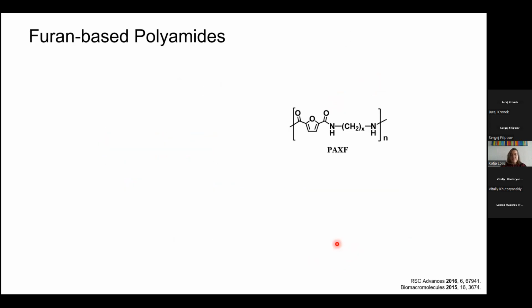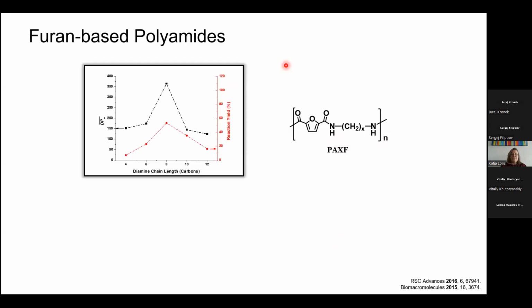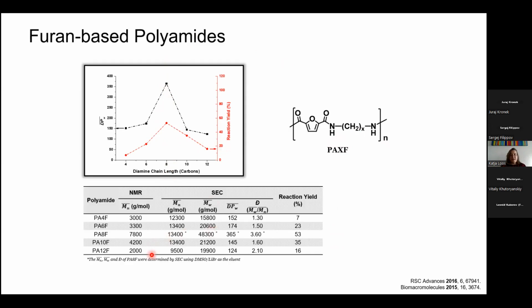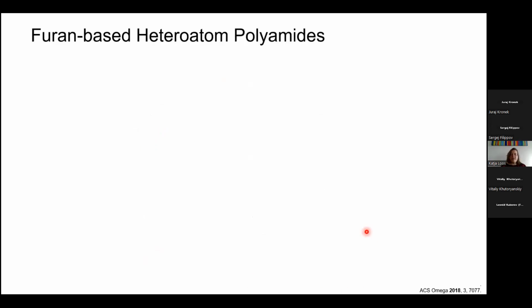And again, also here we screened different diamine lengths, and you see again that the enzyme prefers a diamine with a length of 8 carbons in the chain, and this is again sort of the natural length that it's used to from the fat in nature. And yeah, you see again, we don't get the highest molecular weights because of solubility issues, but it's in principle a reaction that we have under control, and where we can do a post condensation. Yeah, and this odd preference comes from the natural selectivity of the enzyme.